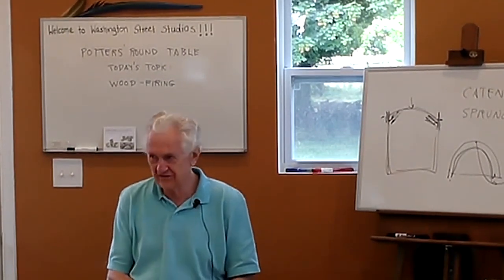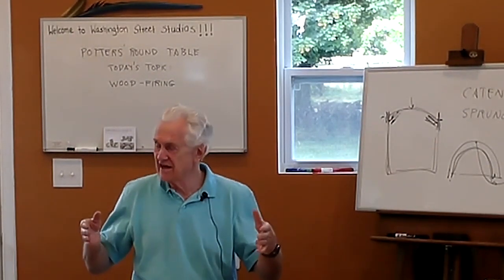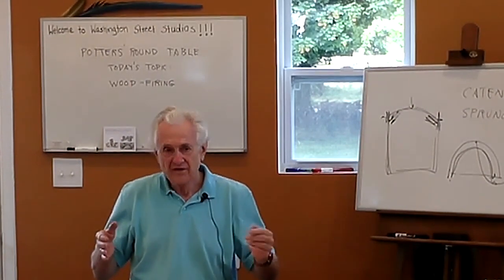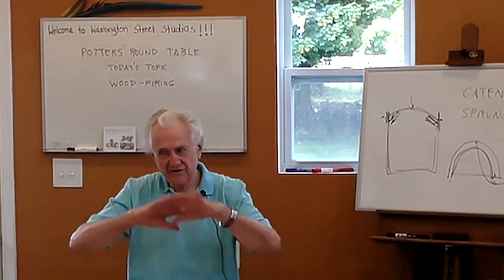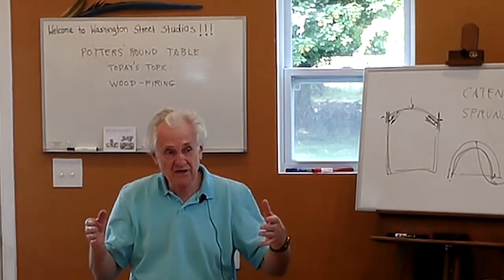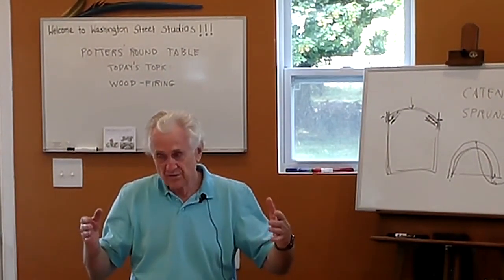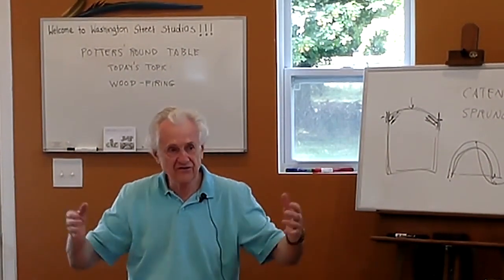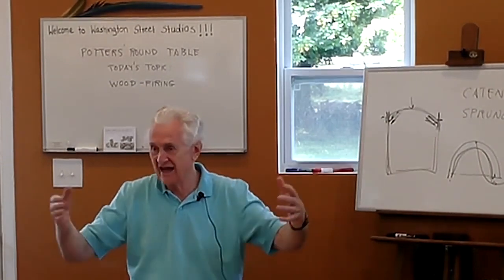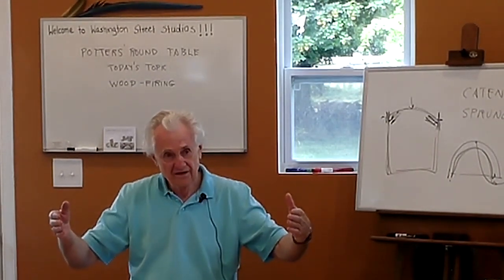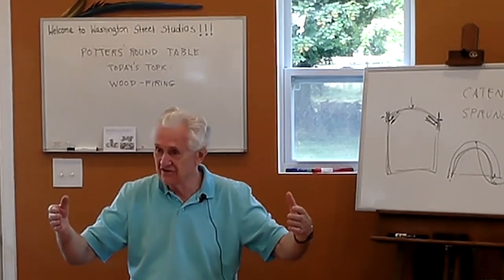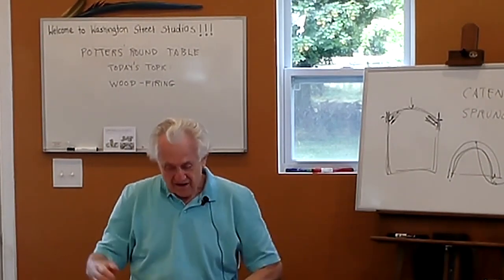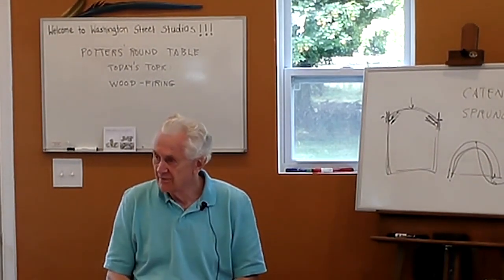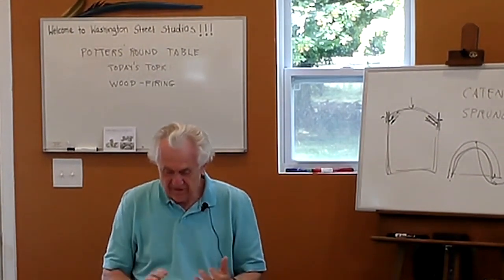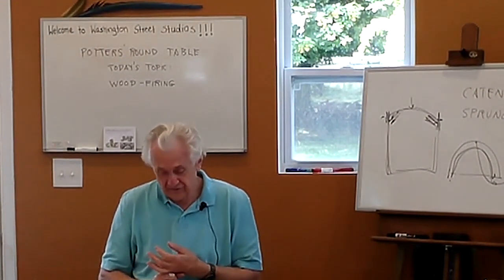They're horrible insulation. You need them to resist the ash, because the ash from the wood is going to land on everything in the kiln, and if you get hot enough, the ash will melt, and it reacts with everything that it touches. So if it lands on the bricks, it'll actually start attacking and eating into the bricks. At least it'll coat the bricks, if nothing else. So you've got to use hard bricks, and they have to be high temperature bricks.